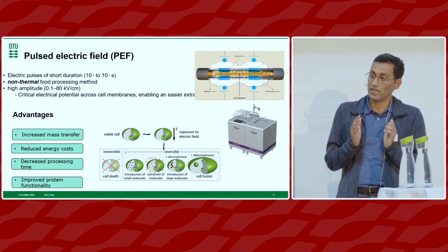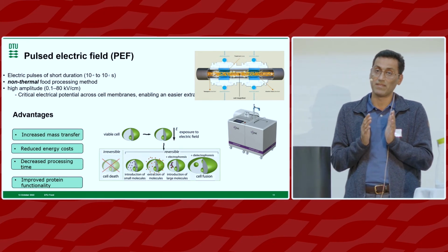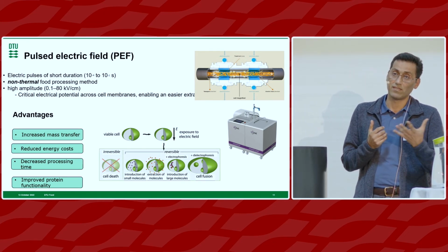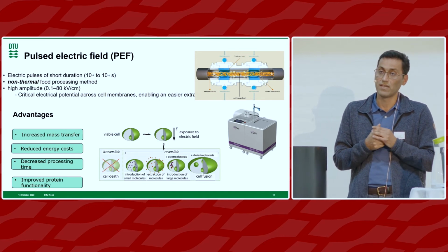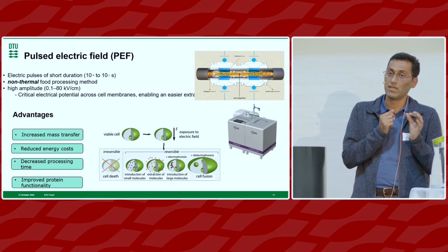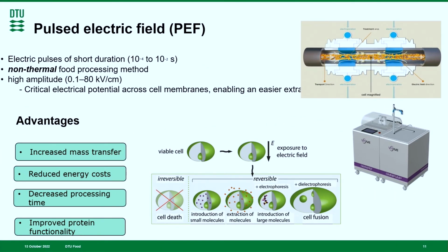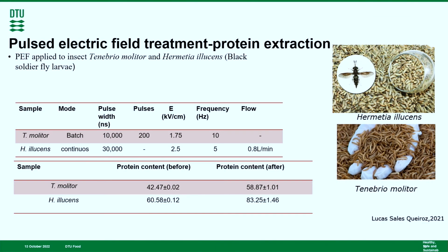The consequence of this treatment is that if you have cells inside your food, like bacteria or other cells, you make some pores in the membrane, and then you change mass transfer, and this way you kill bacteria. So it's good for safety reasons. But you can also use this for other purposes. You can adjust the pore size with this technology so that you can extract ingredients inside the cell. I mean, you can use it in downstream for fermentation, for instance. So when you create something, you can extract those ingredients selectively.